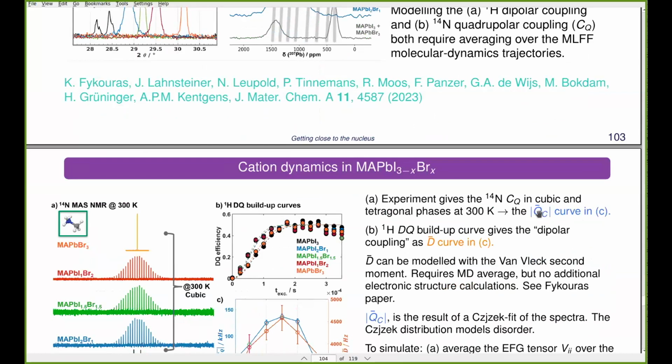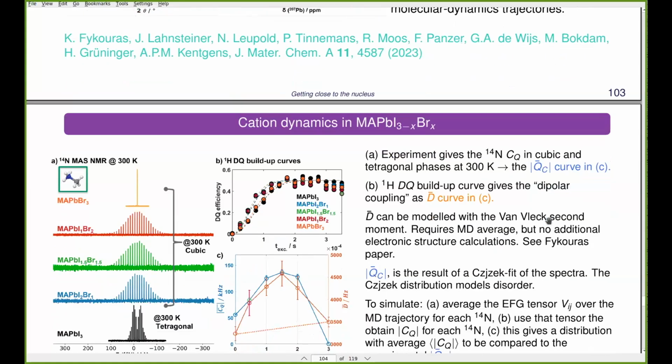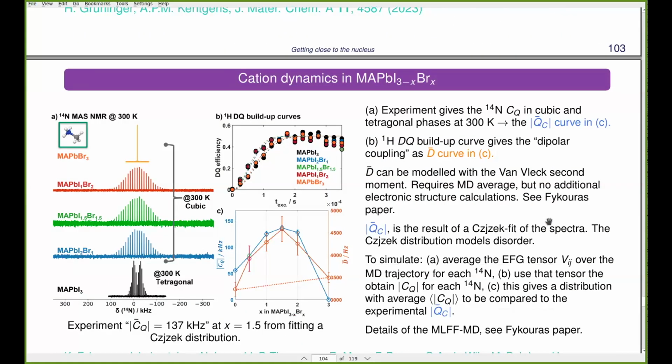So you get a whole range of time frames, say a few hundred, over the whole range of the MD trajectory, very widely spaced, for which you do this EFG calculation again. You collect those tensors all in the same axis, just in the VASP XYZ system, and you average those tensors for one site.